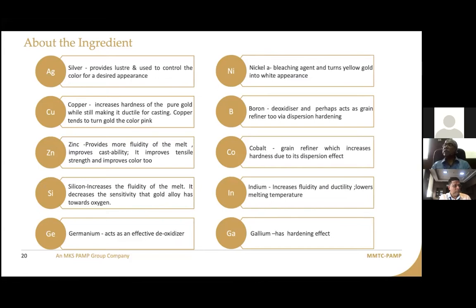Going to nickel, nickel is added for bleaching. That means it imparts a white color. But we know that nickel melts above 1500 degrees centigrade. So naturally, when you add nickel, you have to be careful to maintain a proper temperature, so that porosity or the gas-metal and mold-metal reactions don't affect your jewelry.